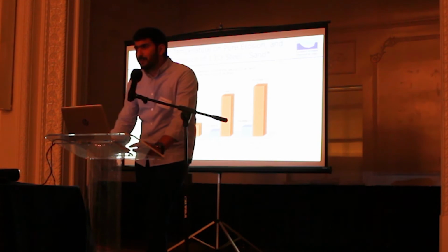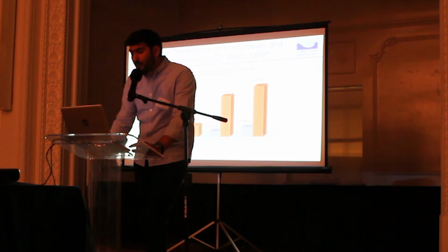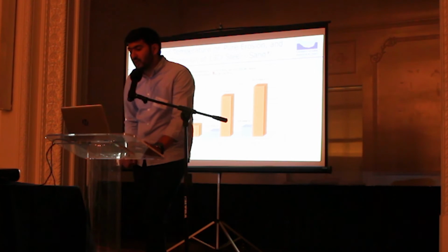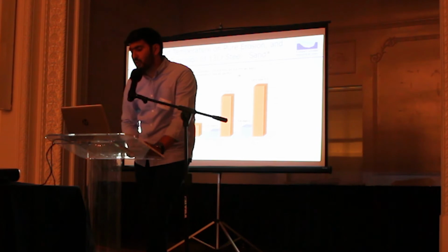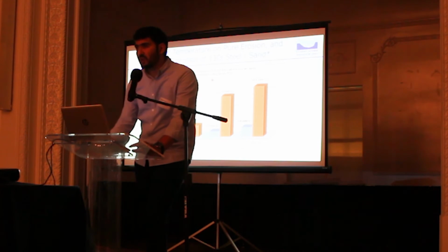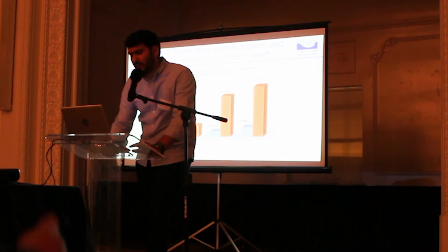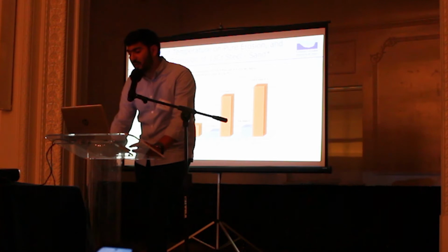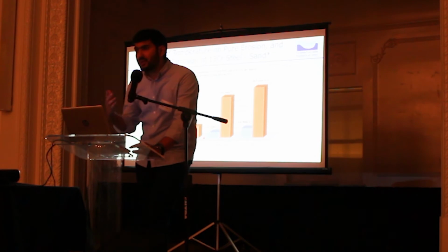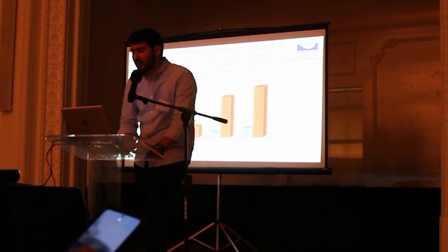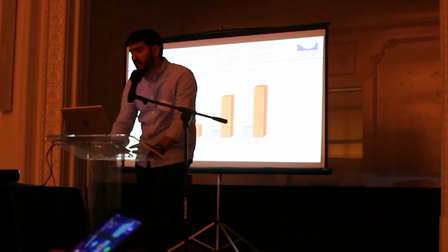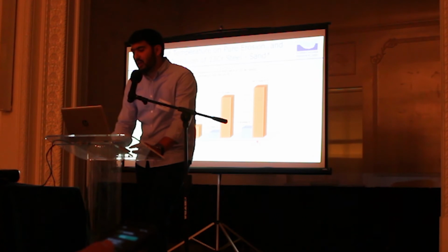Rincon also studied the effect of temperature on the synergism between erosion and corrosion for 13 chromium steel. He conducted pure erosion and erosion corrosion experiments on 13 chromium steel with sand in a single-phase flow loop with a direct impingement configuration, with a liquid velocity of 15 feet per second, a pH of 4.4, 2% by weight sand concentration, and 50 psi CO2 gas. As before, the vertical axis represents penetration rate in mils per year, and the first two columns represent the comparison between pure erosion and erosion corrosion at 70 degrees, then the same comparison at 150, and then a comparison at 200 degrees Fahrenheit.